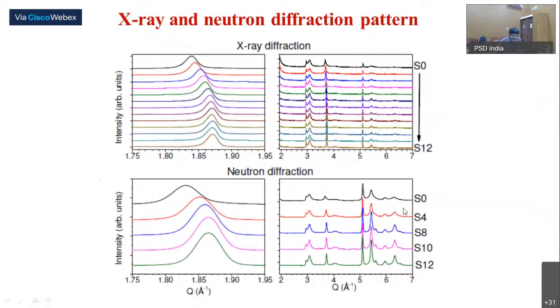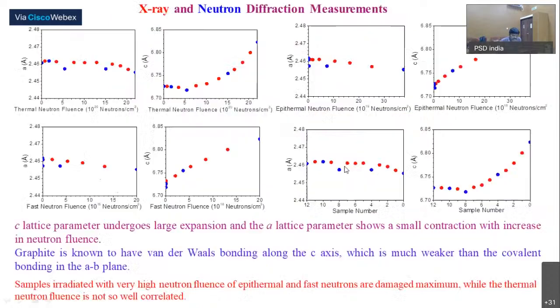And these are the various diffraction patterns from neutron diffraction, and this data is plotted here. A and C are plotted as a function of thermal neutron fluence, epithermal neutron fluence, fast neutron fluence, and sample number. For the sample which has seen maximum fluence, we have given 0. So this has seen maximum fluence, and this is minimum. This is the fresh sample.